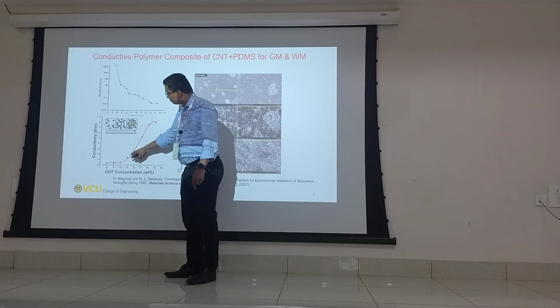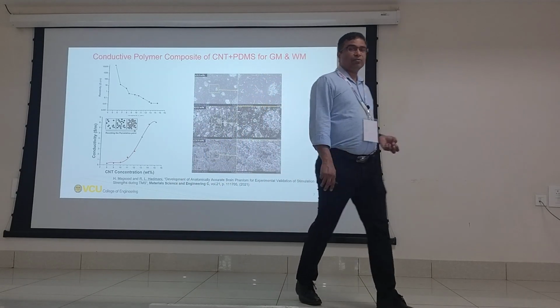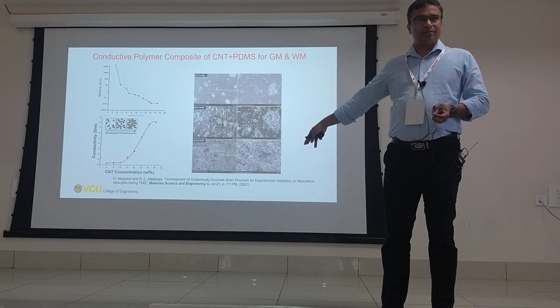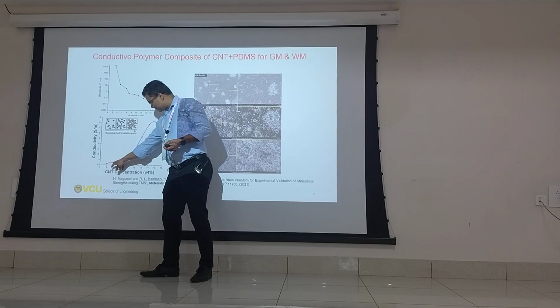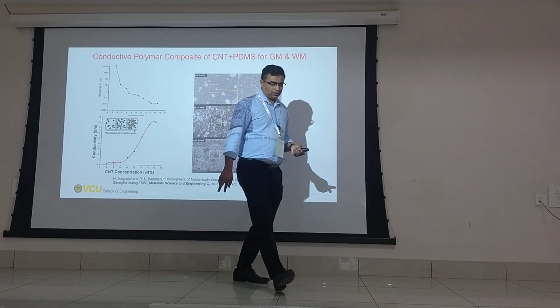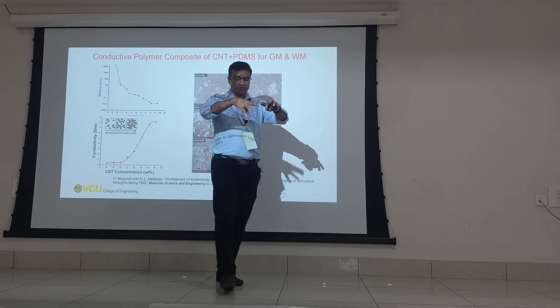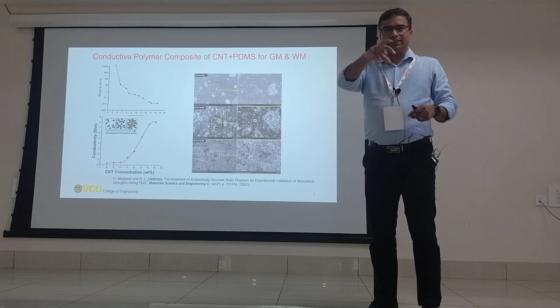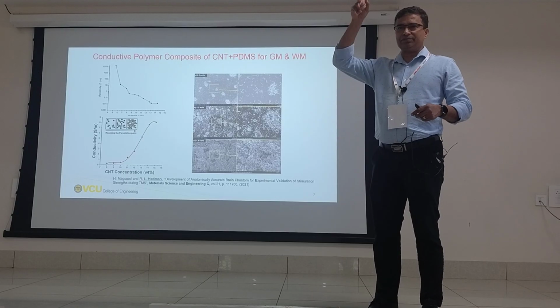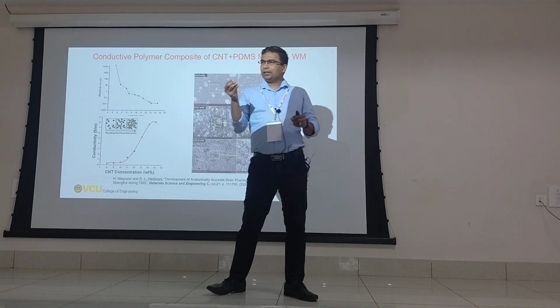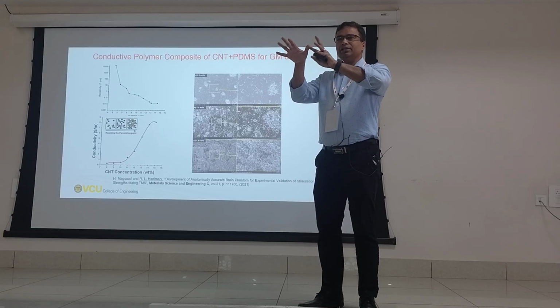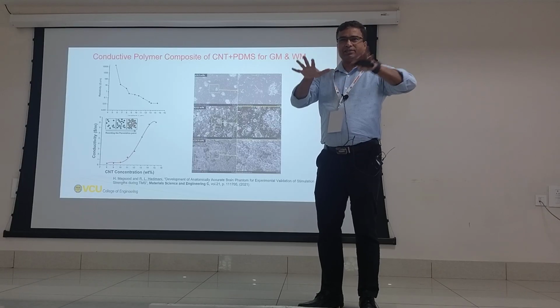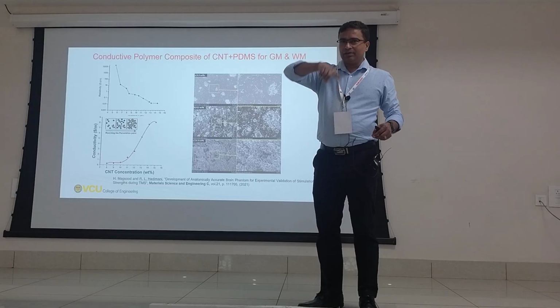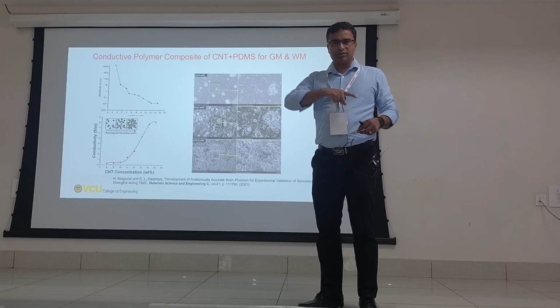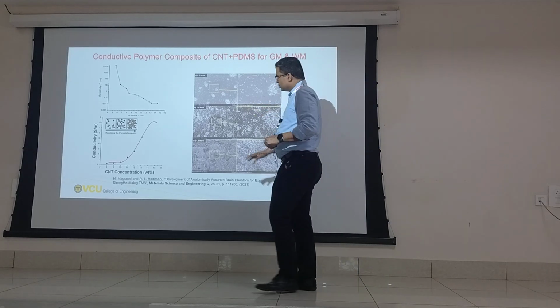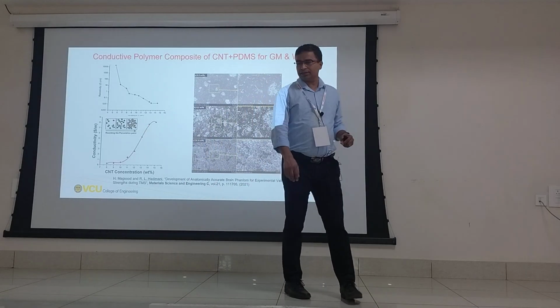Okay, so there is a certain point where the conductivity shoots up. Do you know why? By the way, it's called the percolation point. Do you know why the conductivity increases slowly and at a certain point it suddenly jumps? So think of carbon nanotubes, right? If you start adding them, they create paths for electrons to conduct, right? That's how the conductivity increases. But after a certain point, you have added so many carbon nanotubes that you form a network. Suddenly they're touching each other, right? As soon as that happens, there is an easy path for electrons to transport the charge. So your conductivity suddenly increases.